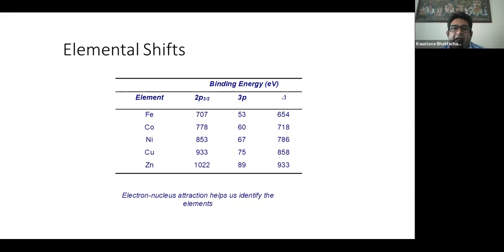So for iron, for example, if we are getting 707, we usually say the iron is in the form of iron 0. Equivalently, if we get it for cobalt, it is in the elemental state. We say cobalt is in the form of cobalt 0. And if we get nickel, equivalently, 853 is for the metallic nickel, and 933 is for the copper.